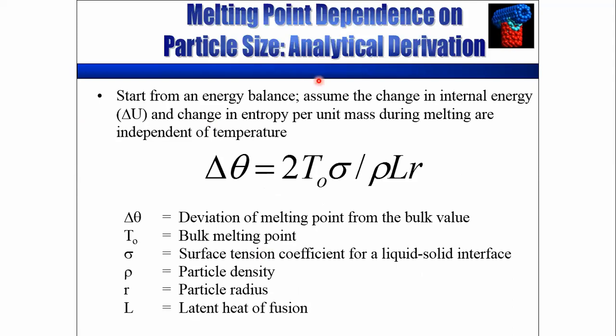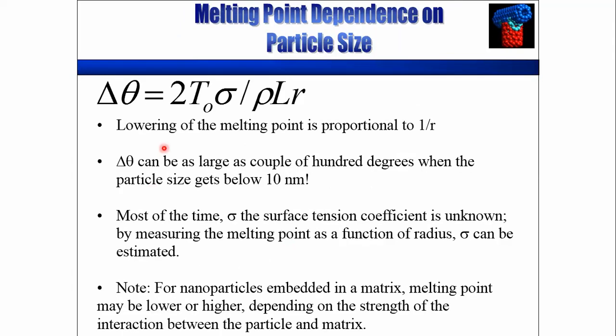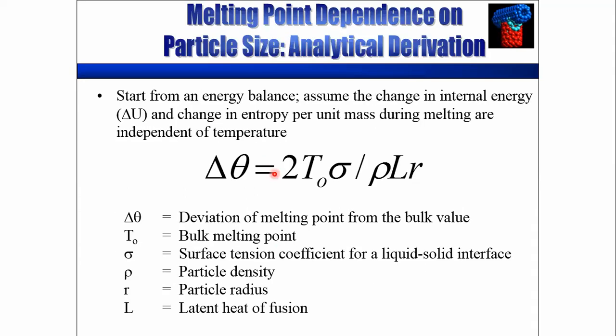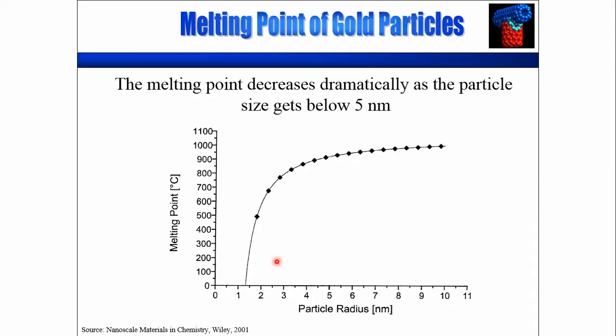So how does it change? The change in melting point of the materials is given by this formula: 2 T naught sigma by rho L R. R is the particle radius, so it is dependent on 1 upon R, and the latent heat of fusion and other parameters are there, but the change depends on the decrease in size. If there is more change in temperature, that means the radius is much smaller. So lowering of the melting point is proportional to 1 over R. Delta theta can be as large as a couple of 100 degrees when the particle size gets below 10 nanometers. So you might have seen here how drastically it changes at lower scale.